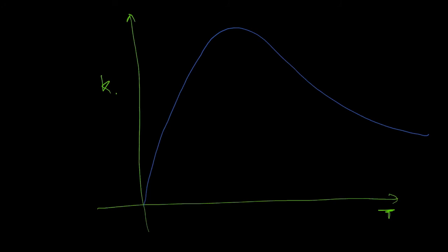Actually, thermal conductivity is entirely determined by those movements. If we use the kinetic theory of gases, it comes out to be one third of heat capacity, group velocity squared, and tau. That's how thermal conductivity is given. C is the heat capacity. Vg, if you remember, we did an example today also, is the slope of this line, which we determined today. Tau is the lifetime, how frequent the collisions between the phonons are.